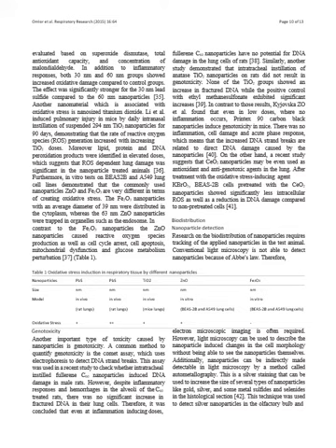In contrast to those results, Jacobsen et al. found that even in low doses where no inflammation occurs, Printex 90 carbon black nanoparticles induced genotoxicity in mice. There was no inflammation, cell damage, and acute phase response, which means that the increase in DNA strand breaks is related to direct DNA damage caused by the nanoparticles.